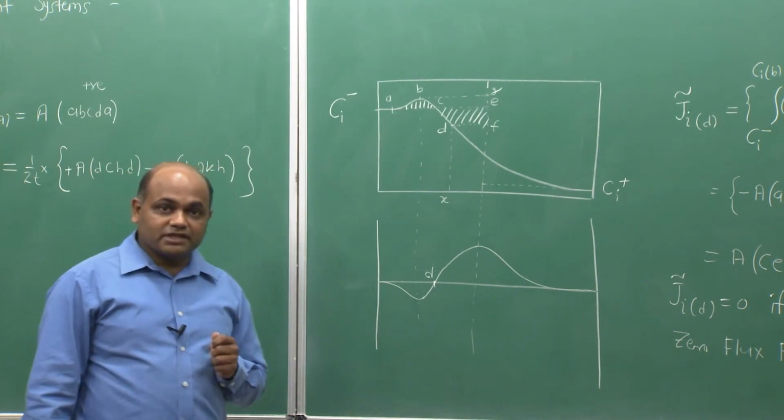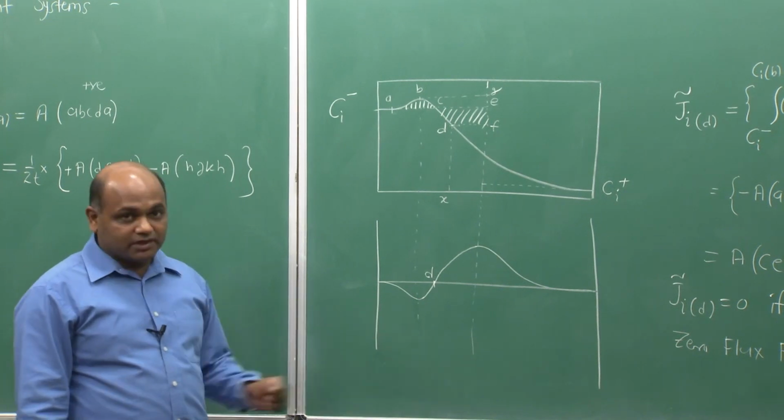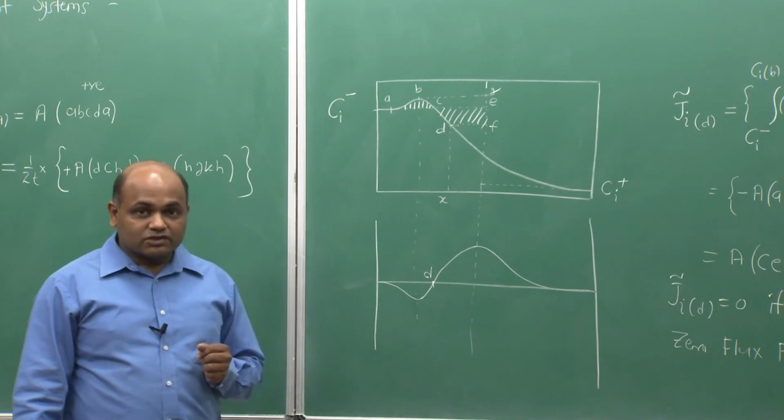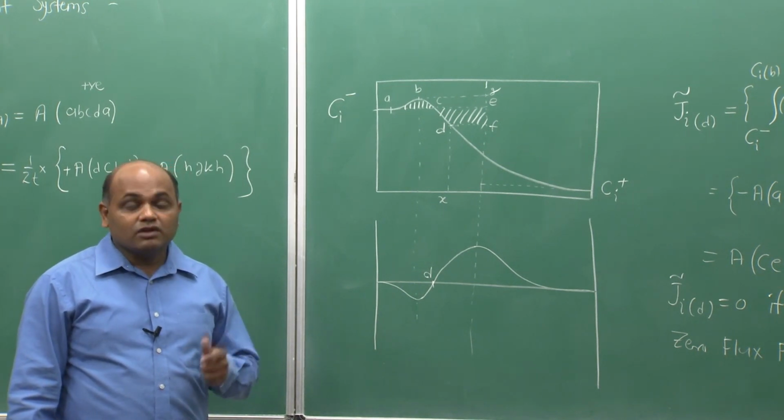The existence of a ZFP in the flux profile of a component in a multicomponent diffusion couple indicates that there are strong diffusional interactions or strong cross effects.